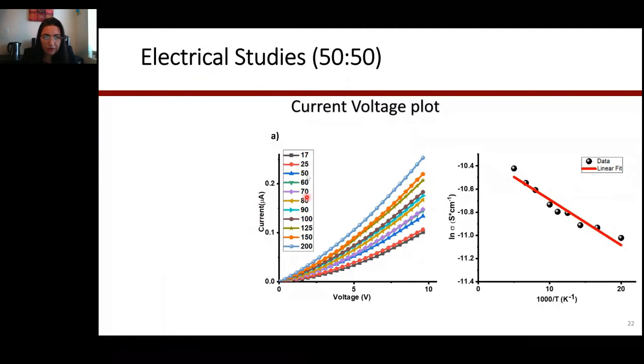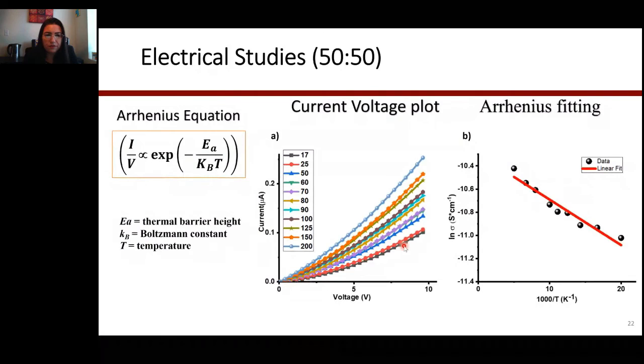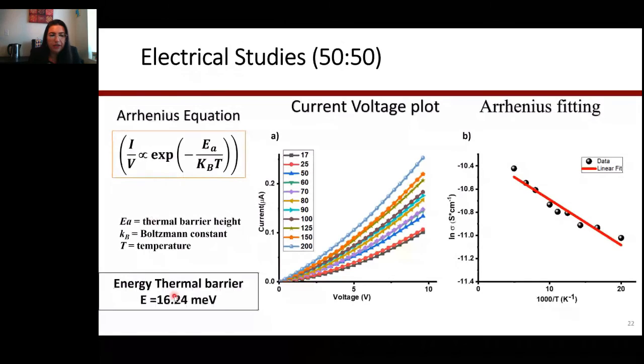Sorry, I should have a unit here of the temperature. So this is varying temperature, and using the heat, we can determine the thermal barrier. So this Ea over here is how much energy we need for the electrons to start flowing. This value is a little bit higher: if we have just graphene it is about 8, and here it is 16.24. So that means that we need a little bit more energy for the electrons to start flowing. That is really the semiconductivity that I mentioned before, the on and off switch that you would need for the electronic application.